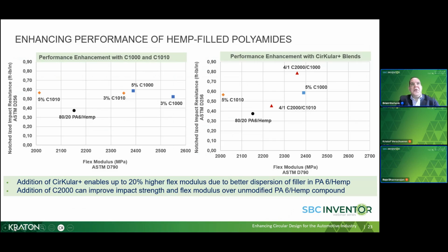Well, thank you, Raja. So beyond the polypropylene blends with natural fiber, Circular Plus can add value in modifying hemp-filled PA6 as well. So this absolutely works with polyamides. Hemp actually has a bigger effect on PA6, where 20% loading of hemp reduces the impact performance of neat PA6 by 70%. So it's a lot. That's without any modifiers added.